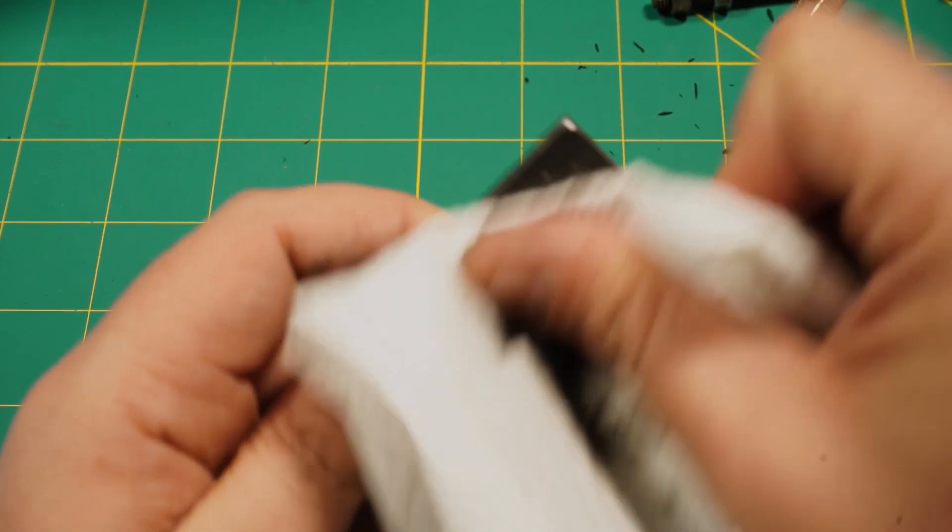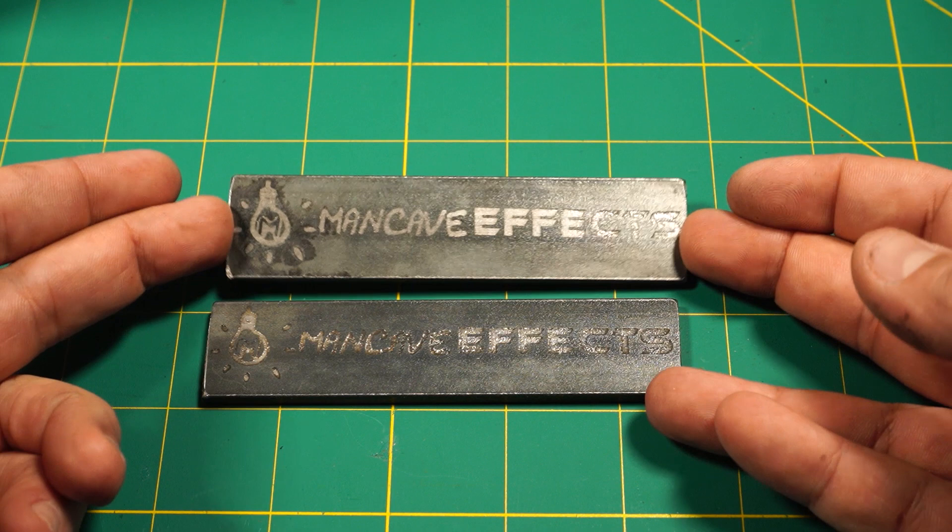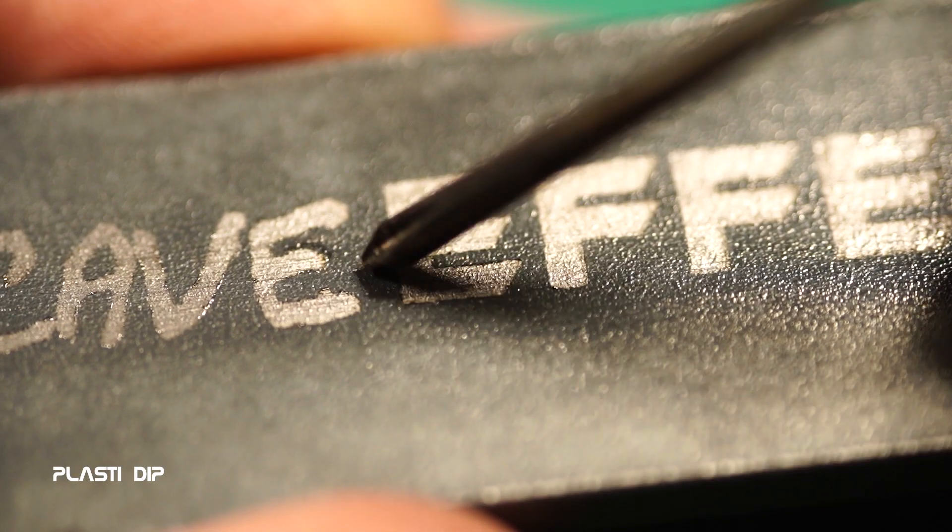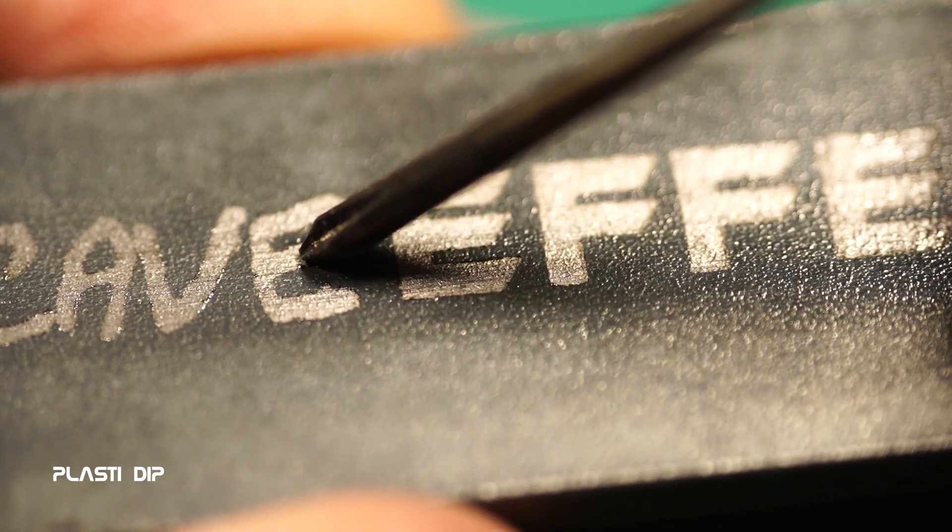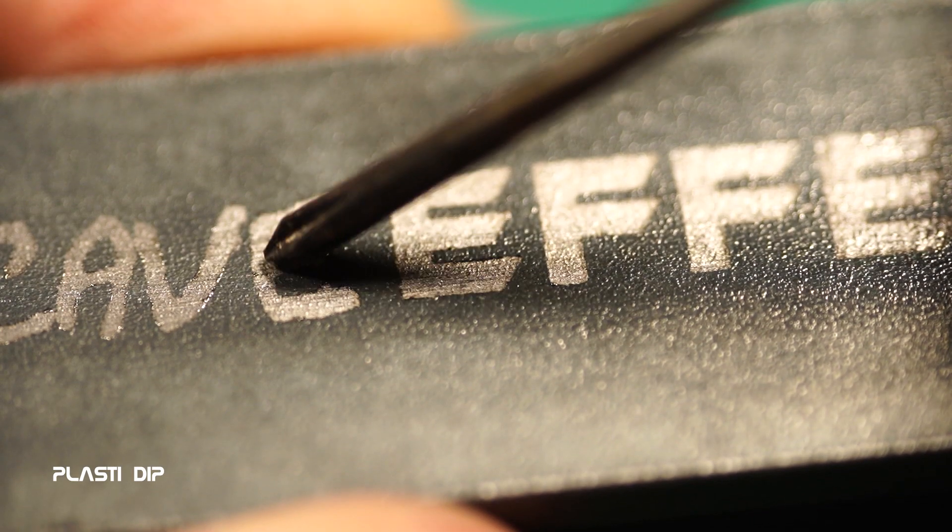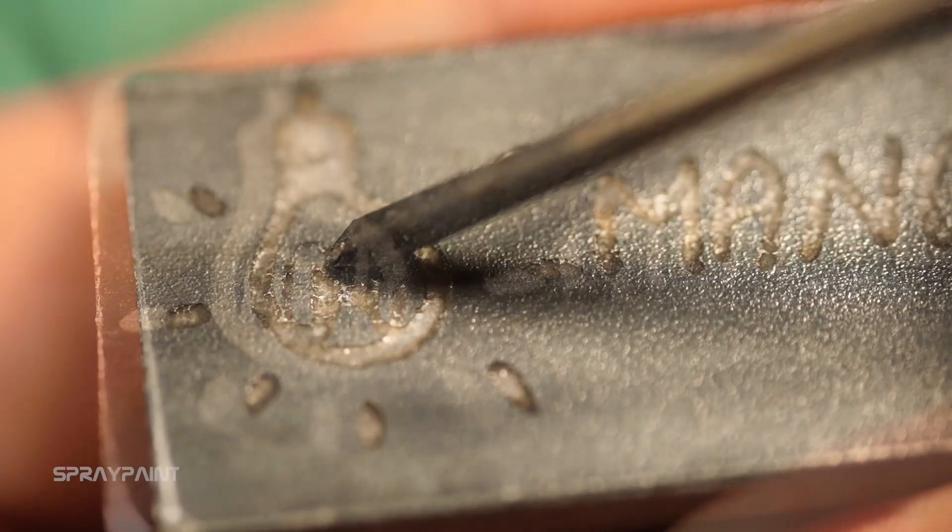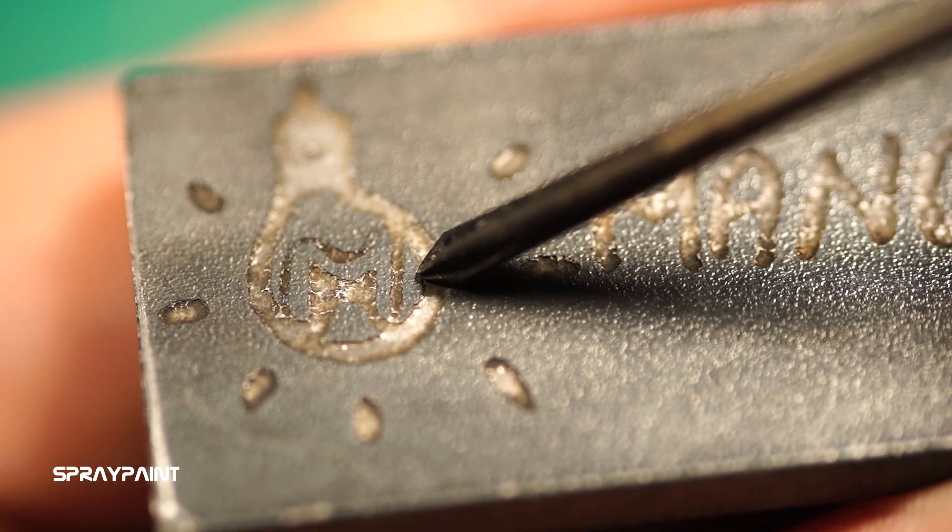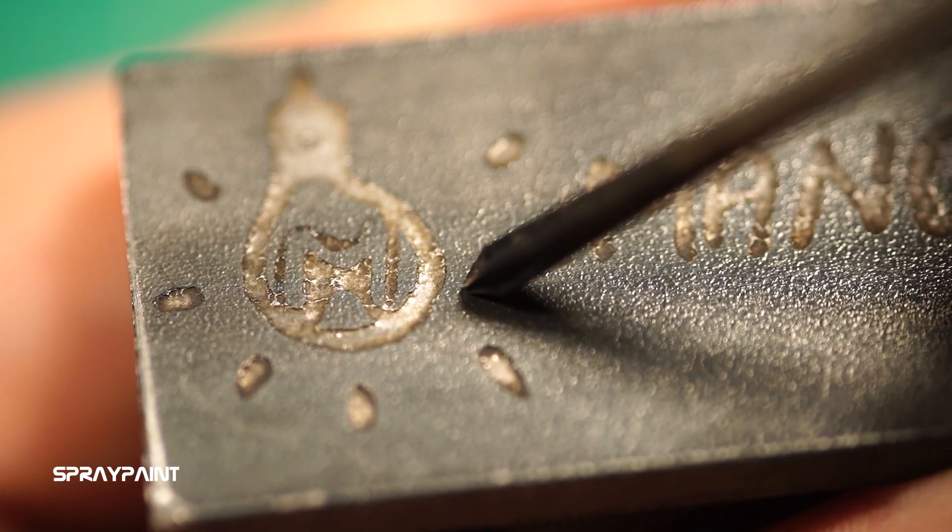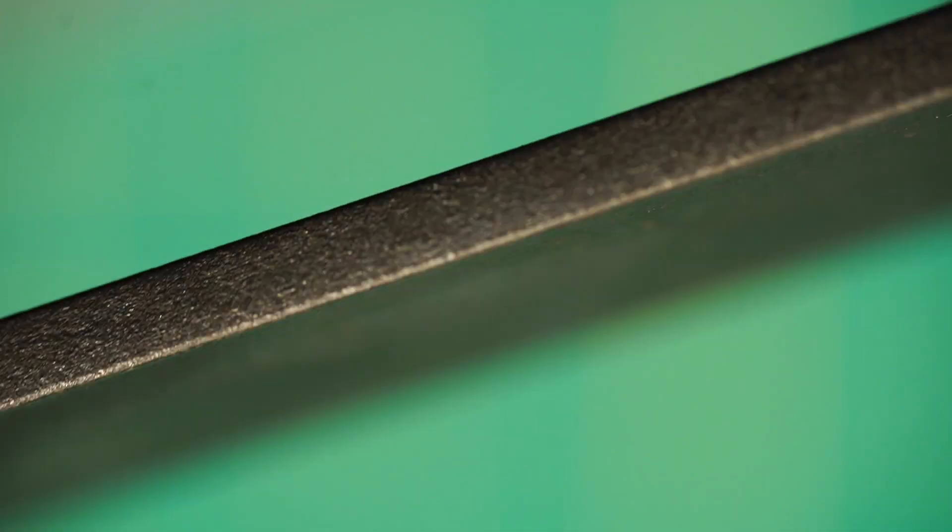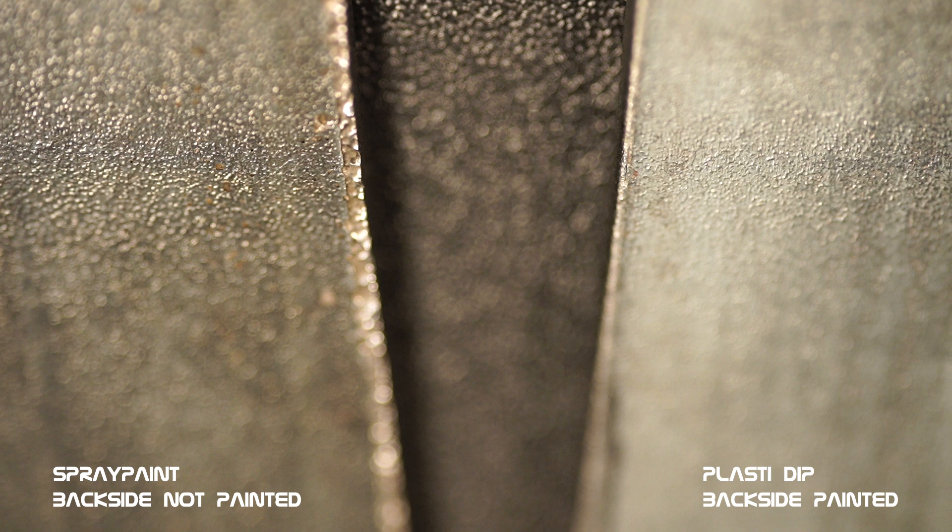For the spray paint I need to use some acetone to wipe off the paint and that comes right off as well. Now both pieces look absolutely perfect. The etching on the Plasti Dip part seemed to be a bit better, but I think this is due to the fact that I rastered that piece twice with the laser. I only covered the front side of the spray paint piece and that actually caused the edges on the back side to be eaten away. Comparing to the Plasti Dip part that was entirely covered, you clearly see a difference.